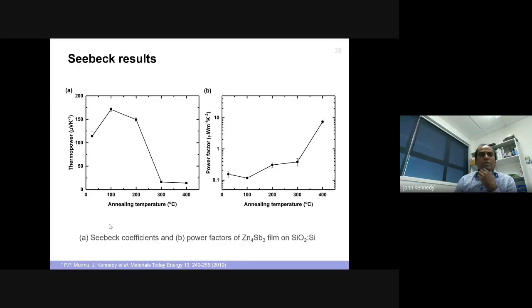We looked a bit more at the Seebeck coefficient, which is a key element, as I said before, and that's reasonably high, up to 200. When you anneal, the Seebeck goes down. But we have to put it in the context of alpha squared sigma, which is the power factor, the combined thermoelectric efficiency. Even though you're losing a little bit of Seebeck here, you're gaining hugely in the conductivity. So the alpha squared sigma power factor is reasonably high for 300 to 400 degrees. So there is a balance. By narrowly tuning the electrical conductivity and the Seebeck coefficient, you can improve the power factor, which is related to the efficiency.